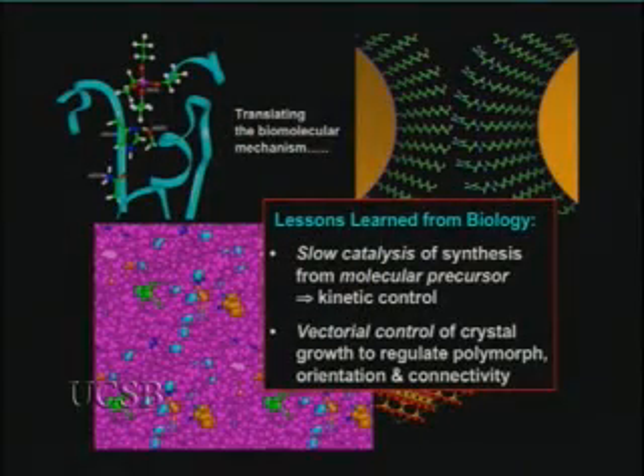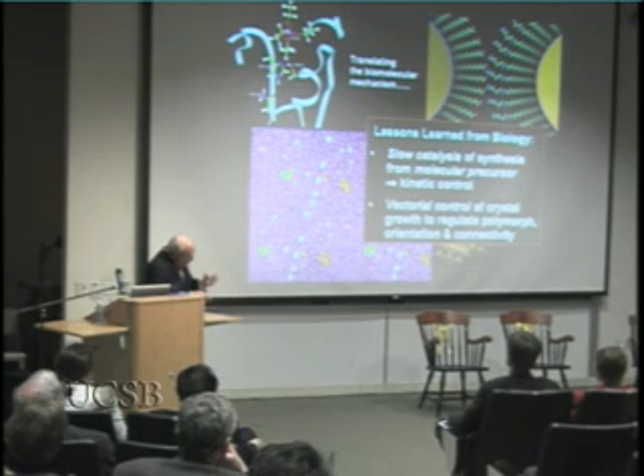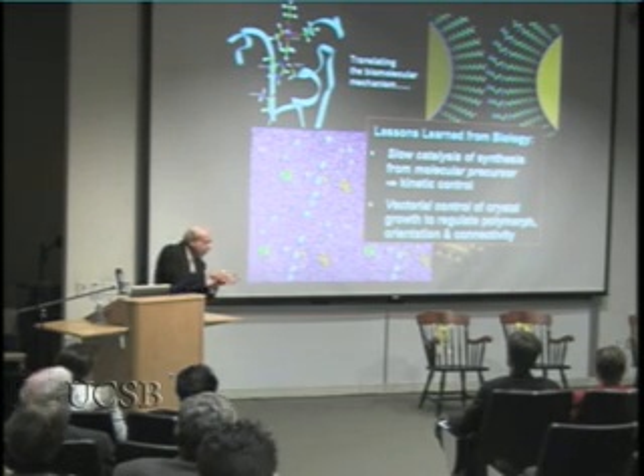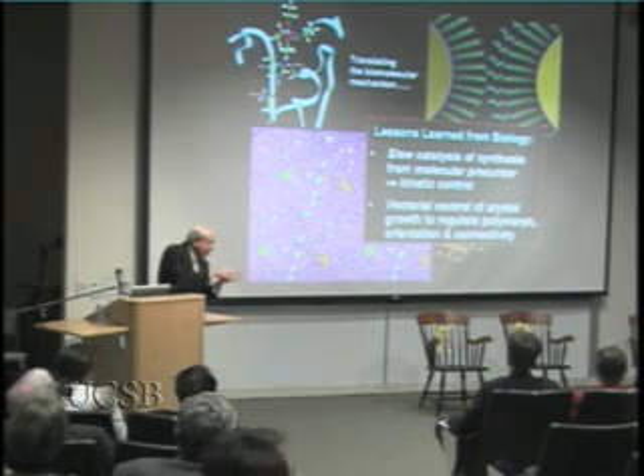First, I didn't mention, but this enzyme is very, very slow in its catalysis of synthesis from the molecular precursor, providing an opportunity for what my esteemed friend and colleague Galen Stucky taught me to appreciate as kinetic control of the reaction, providing the opportunity for the weak cooperative interactions of the growing nanocrystals of semiconductor with the protein surface to dominate and control the structure, allowing you to defeat the thermodynamic default and get crystal forms that you otherwise could not obtain at those low temperatures. Kinetic control, slow catalysis, we can do that in several ways fairly easily. But how do you get rid of the template?